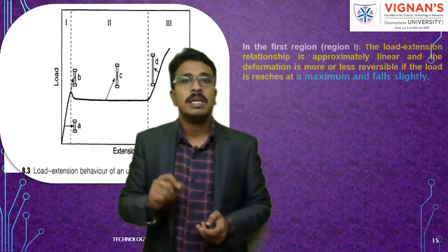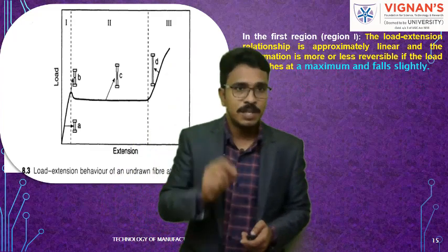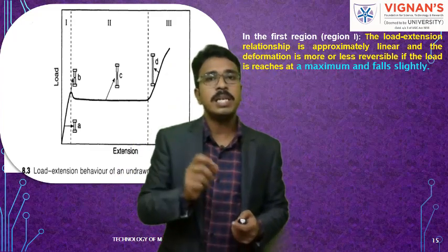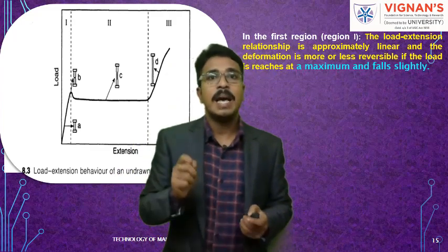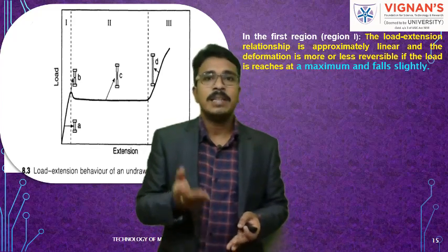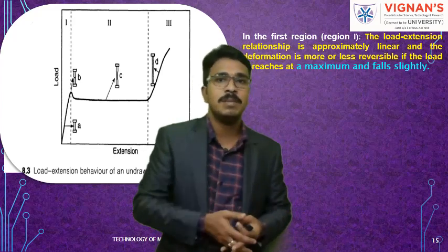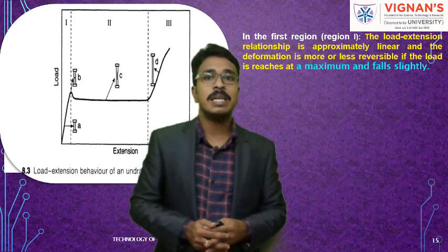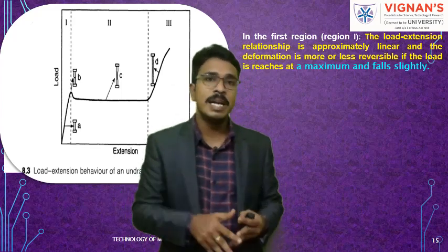In this first region, the load extension relationship is approximately linear and the deformation is more or less reversible if the load reaches a maximum and falls slightly.